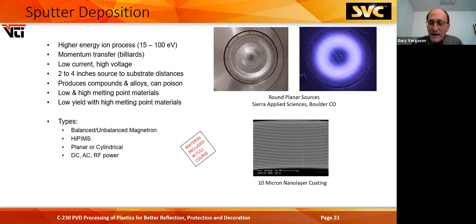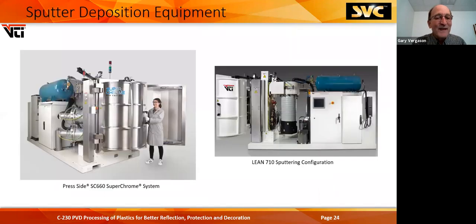And this is just a sputtered coating over here, a 10 micron coating. This is actually on an acrylic 4,000th diameter fiber. So this is quite a coating. The heat control that we had to maintain, that's about a 30 hour cycle. There's a lot more behind the curtain here too.